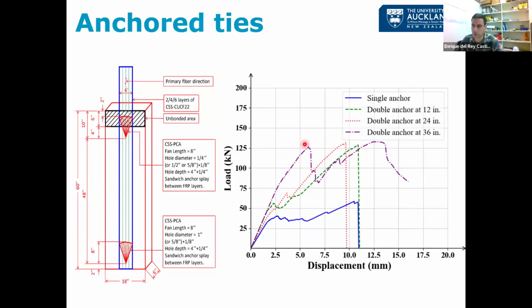This is also the end of Junri's thesis. So we are hoping to have a model where the designer can basically calculate these figures. So it could be A, B, C, D, E, or if we have several anchors, it would be A, B, C, D, E. But this is probably the end of that. We've done a whole lot of tests with shallow anchors because we have very thin topping slabs, sometimes 50, 75 millimeters. So we have tested that as well. We have tests on anchors installed in cracked concrete. So we can design for all of those different scenarios.